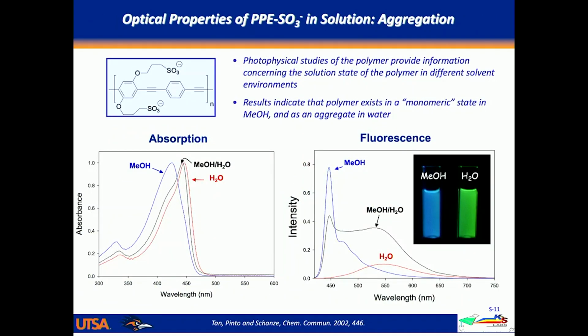Okay, so I'm going to start kind of at the beginning in my own group story. And this has started out with just fundamental work where we were beginning to explore the properties of these water-soluble conjugated polymers. And as I mentioned before, we had synthesized this sulfonated polyphenylene ethynylene. The molecular weight of these materials typically is around 20 to 50,000 Daltons. That corresponds to in the range of maybe 100 to 200 repeating units. So they're moderately sized molecular weight polymers. And as I mentioned before, they're quite soluble in water, but they're also soluble in polar organic solvents like alcohols.